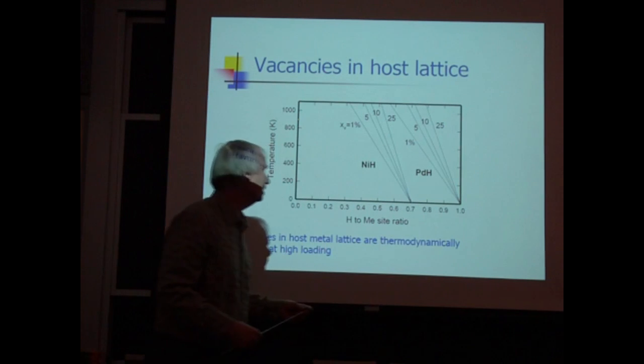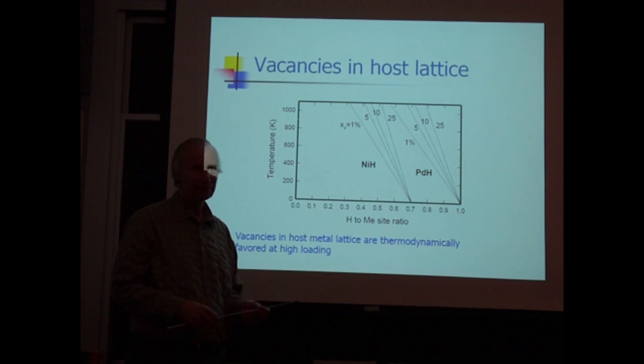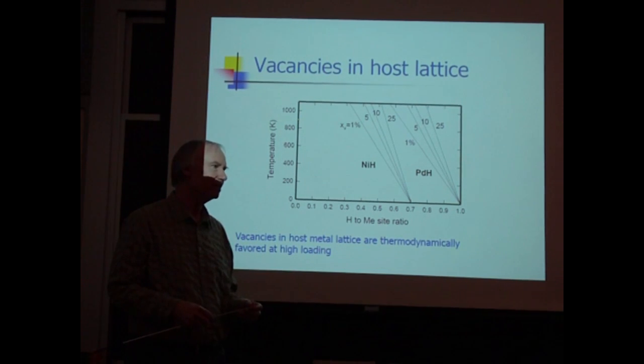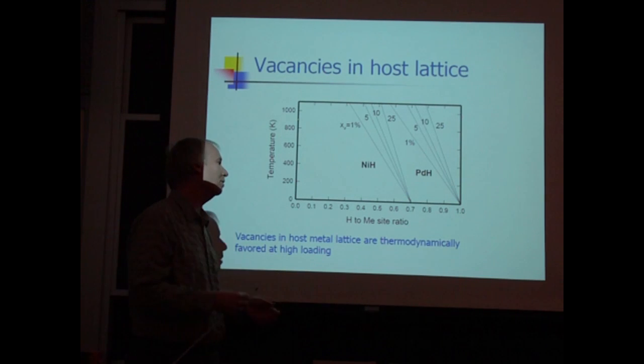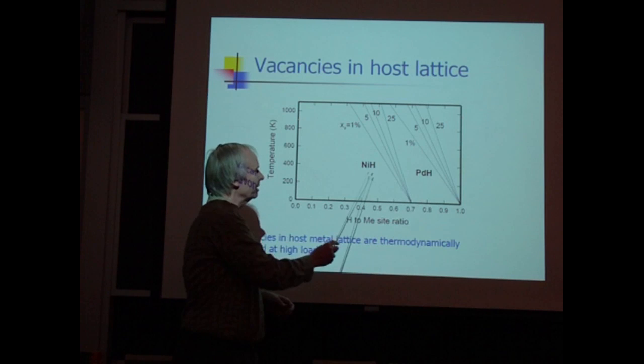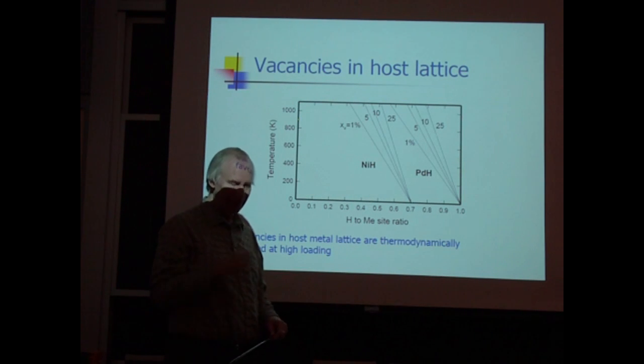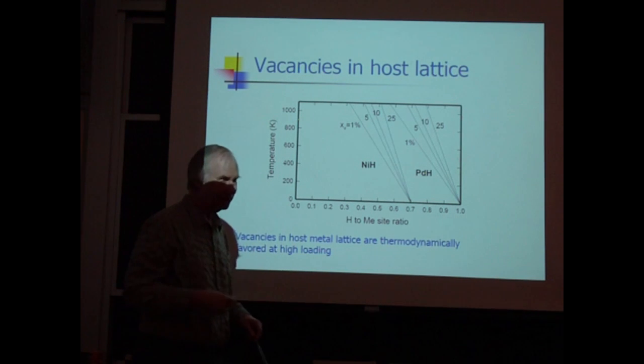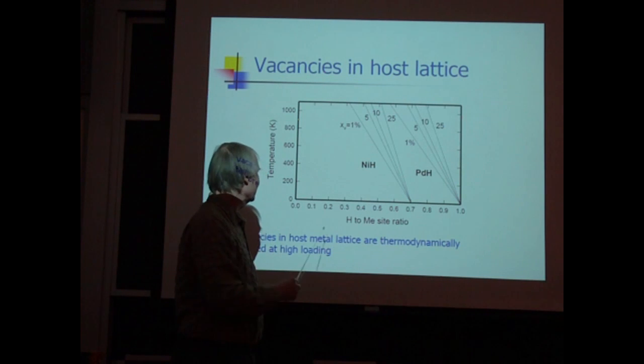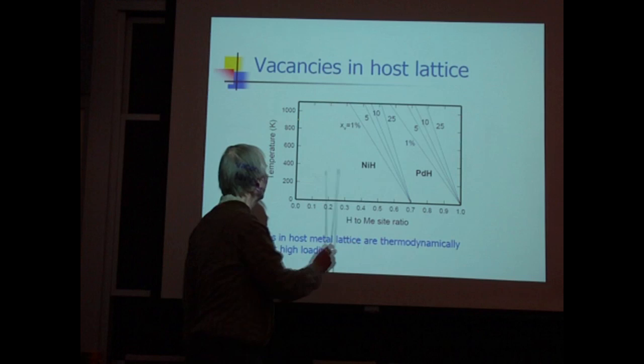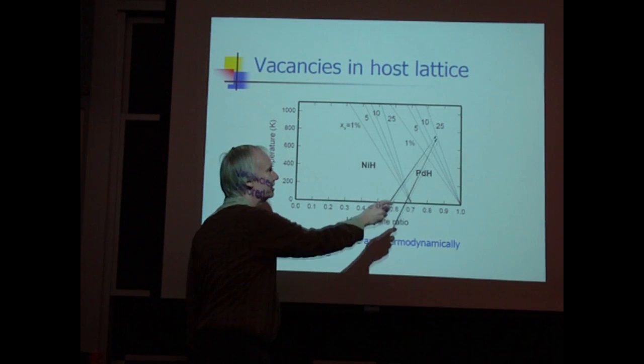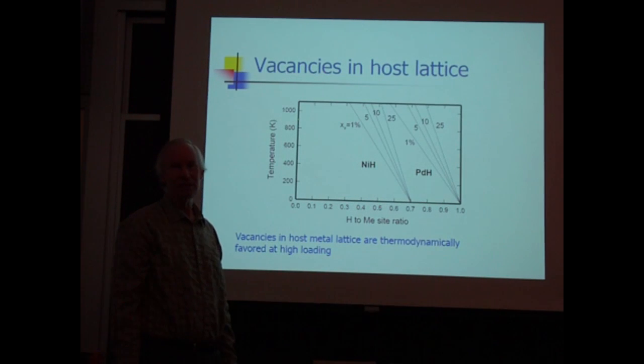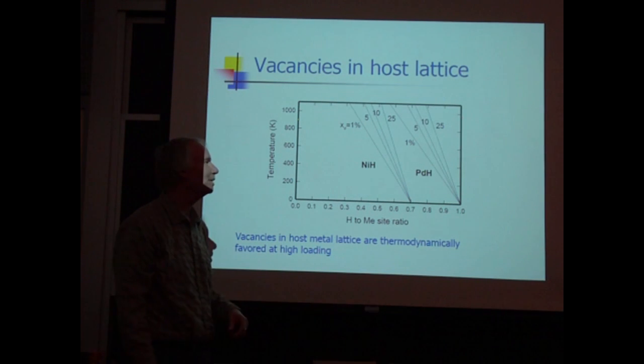Back in the mid-90s, I was very interested in this, and I took the available thermodynamic data for stabilization of vacancies, and I calculated it out to see what it would mean in terms of how many vacancies at what temperature, at what loading. I calculated this for palladium hydride and for nickel hydride from the existing data. Since that time, more experiments have been done, there are better models, and I very much need to update this curve. But the conclusion is that if we load palladium up to 0.95, and if we operate near room temperature, the fraction of vacancies we would expect would be 25% in this model. And 25% is the maximum number of vacancies you can get in an ordered phase called the Fukai phase, which I mentioned last time, and I'll talk more about this time.